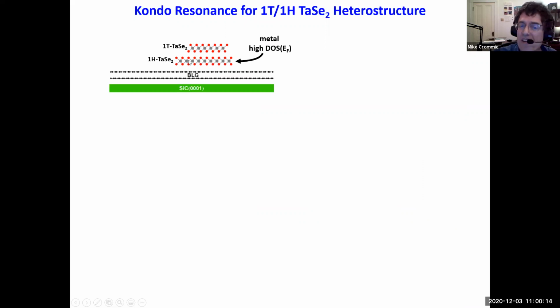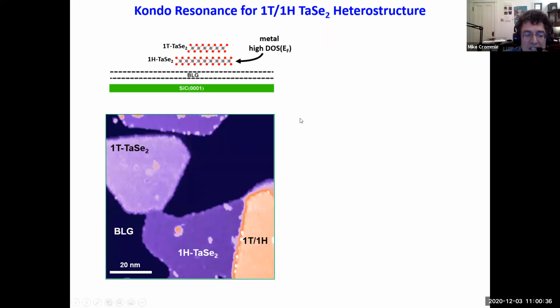And the reason why we did that instead of just looking at 1T TaSe2 on the graphene is because the density of states of 1H TaSe2 is bigger, because the Kondo temperature is too low if we put 1T TaSe2 on bilayer graphene. But on 1H TaSe2, we're going to get a higher Kondo temperature. And so we adjusted our growth parameters to get this kind of a material. And so here you can see it in the STM image.